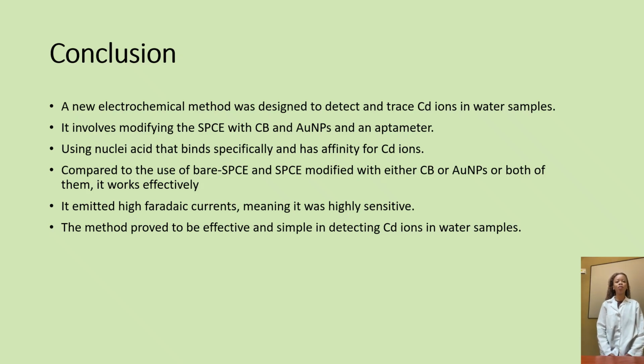Conclusion: the modified SPCE with CB-AuNPs and an aptasensor was developed to detect cadmium ions in water. It uses a DNA aptamer that has affinity for and binds this cadmium ion. So the sensor works effectively in comparison with the bare SPCE or the SPCE with CB. The sensor detected very small amounts of cadmium, as low as 0.14 parts per billion, in a range of 1 to 50 parts per billion, and showed good accuracy, stability, and high Faradaic current sensitivity. This method would have been the most effective if the repulsive forces between the aptamer and the ferrocyanide redox probe did not affect the shuttling of electrons. The method uses the aptamer's ability to specifically bind to cadmium, avoiding issues other methods face, like interference from other metals. Overall, it offers a simple and effective way to detect cadmium in water.